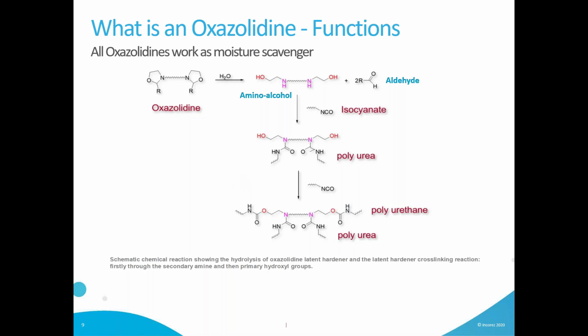If you look at the oxazolidine molecule here, which is a bisoxazolidine, like Incozol 4 and EH, once it reacts with the water, you will actually generate an amino alcohol that will be reactive in your system. First of all, the amine function will react with the isocyanate to generate polyurea, while the hydroxyl function will cross-link your system as a polyurethane. So instead of having a moisture cure system, you actually have a moisture trigger system. It's slightly different because this means you only need the water to start the reaction, but once the oxazolidine has ring opened, it will actually drive your overall curing in your formulation. You won't need moisture in the rest of the reaction.